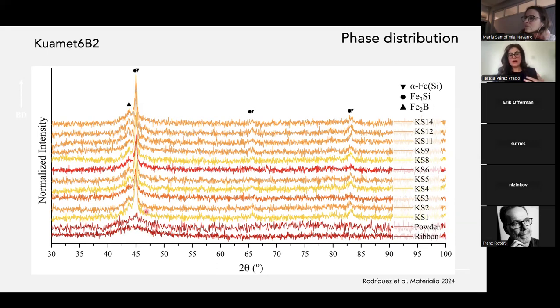But if you look up, all these samples, these are cubes manufactured within all this window, different processing conditions, but for all of them, we do have a bit of a wide halo here, but also there is clearly a superposition of this sharp crystalline peak. So no matter what processing parameters we use, even in the region where we can retain the shape, we are making a composite, an amorphous crystalline composite.